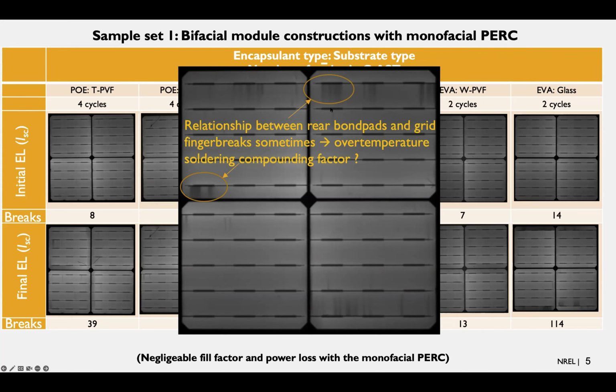And we see a strong correlation, for example, in this yellow circle, between these grid finger breaks and the existence of this rear bond pad. So based on that, I would say there's a good but not exclusive correlation between the rear grid fingers and the breakage that we see. That's about the extent to which I can answer the question, because we haven't done cross-sectional metallography.